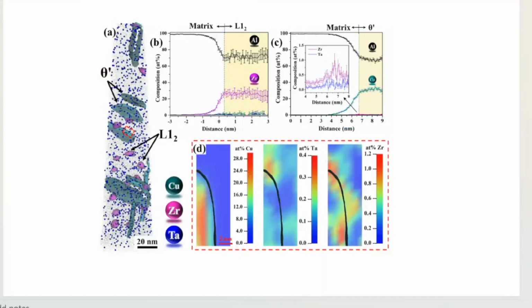And this is the atom probe tomograph of this plate growth. You can see the slice in the D, marked D. That is the plate. And this is a 2D map. And if you look at the 2D map of copper, tantalum, and zirconium at the interface, the dark lines at the interface, you can see that tantalum is only segregating at the tip, whereas zirconium is segregating both on the tip and on the broad face. That means this is tantalum which is responsible for stopping the growth of theta prime precipitate. And that is how we can get very high strength.